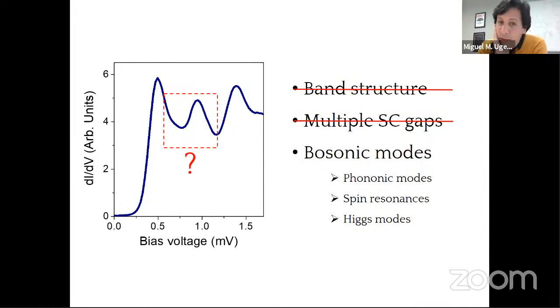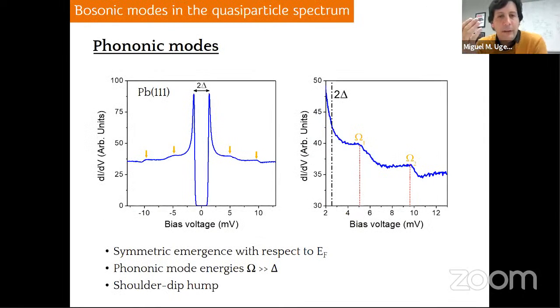So what's left to consider is the existence of bosonic modes, which is quite common in superconductors, not just in unconventional superconductors, but also in conventional ones. For example, we have chosen the three most common ones, which are phononic modes, spin resonances, or Higgs modes. Phononic modes you can observe in conventional superconductors, where the glue is phonons. What you see here is the interaction between the quasiparticles and the mediator, in this case phonons. This is an electron-boson mode that you see here.